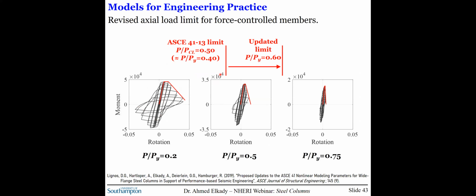As part of these numerical models, we also had to reassess the axial load limit at which a column can be considered a force-controlled member, which means it has no plastic rotation capacity. Essentially, in the previous ASCE 41 standard, the limit was about 40% of Py. So above that, you will need to consider your column member to be elastic, and essentially it loses strength right after it yields. But this can be fairly conservative in light of the current data that we have. By looking at the value of plastic deformation with respect to the axial load, we found that the limit can be relaxed to 60% of Py, which is actually the limit used in the current ASCE 41 standard, ASCE 41-17.